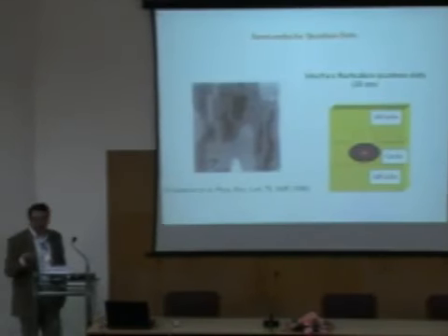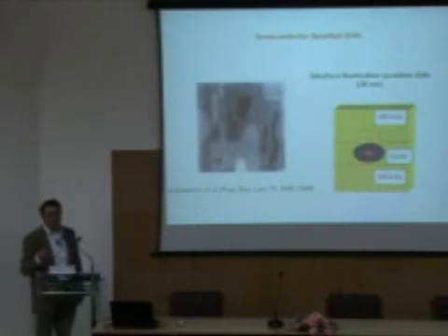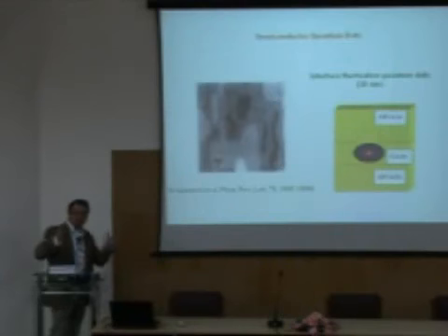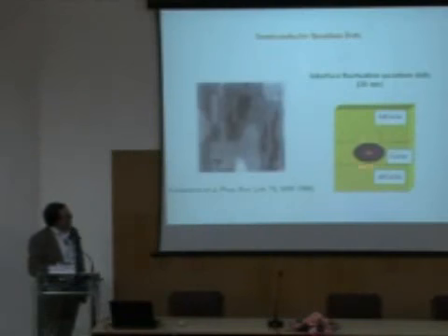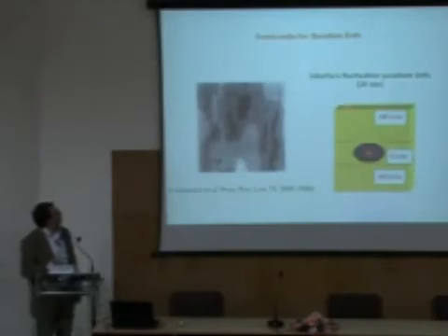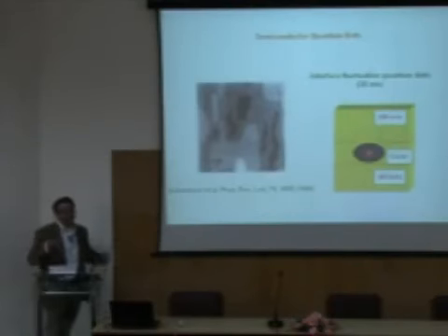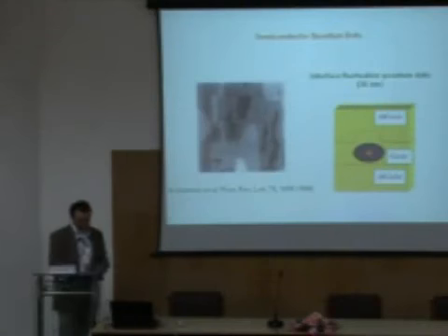So when you shine light, okay, the electrons and the holes will prefer to end up in this region, because they have a larger well, so they have a lower energy. And this is the picture for the quantum well: the exciton tends to be trapped in the region in which you have a fluctuation in the layer of the quantum well. And those are called interface fluctuation quantum dots, and actually the first experiments on single dots were done already in '96 on this type of structures, okay, which are basically random, accidental quantum dots, but they are quantum dots.